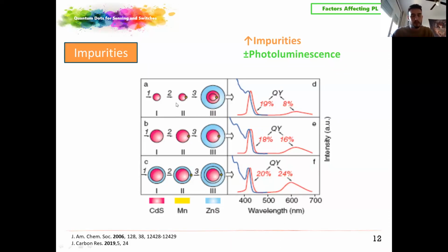They tried to incorporate a manganese atom in different parts of the quantum dot, in order to assess the quantum yield. Here it's inside the core, at the edge of the core and the shell, and in the middle of the shell. And you can see here how, depending on the position of the impurity, the quantum yield is improving. This depends on whether you have a p or n donor; the quantum yield will be modified.